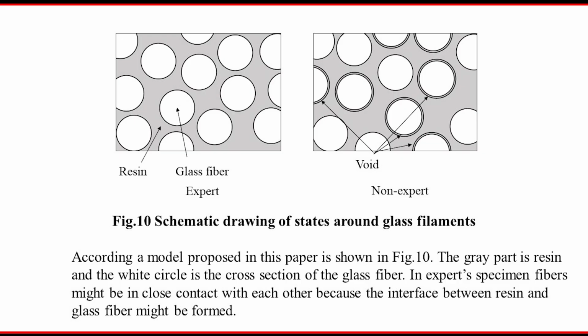And then we observed at higher magnification. We tried to do a more microscopic observation. One of the results is about one filament, one glass fiber. Around one filament, in the case of the expert, there is no void. But sometimes in the non-expert, there is a void around the filament. So we can find this phenomenon.